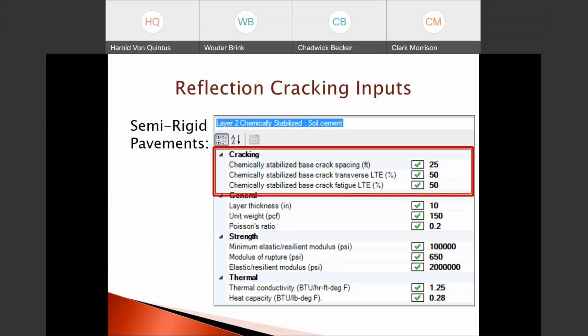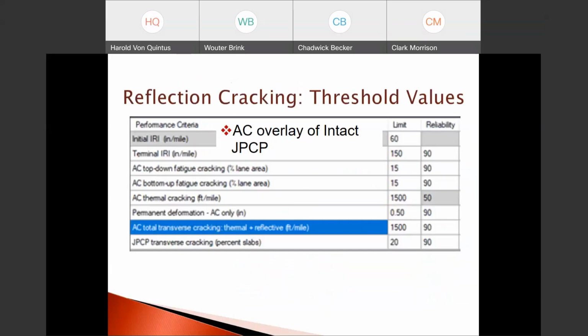The 50% for the transverse and 50% for fatigue, those are the global default values. As I said previously, the low transfer efficiency of the chemically stabilized base can be measured with the FWD. The low transfer efficiency of the fatigue cracks, since they occur later, is typically considered or included as a calibration parameter. This next now, the inputs or threshold values for AC overlay of an intact PCC.